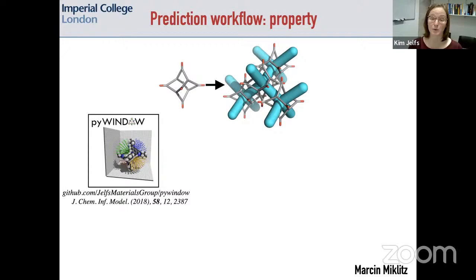But of course, that dynamics consideration is really important because a lot of the early systems, in fact, the first group to report this cage molecule, one of the classic cage molecules, actually wrote in their paper that in this system the cavity is too small to host any guest, like any gas at all. Whereas in reality, that exact same system can even host a xylene molecule within it, but it's just all about that flexibility. But that group had just looked at the crystal structure and seen that the windows were too small for hydrogen and nitrogen, and assumed that it was impossible to get a guest in. But in fact, there's quite considerable breathing motion that means that you can.